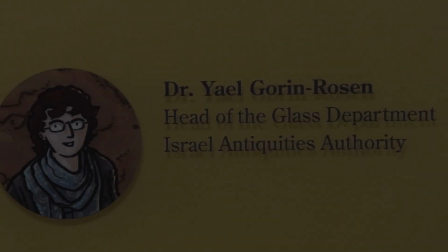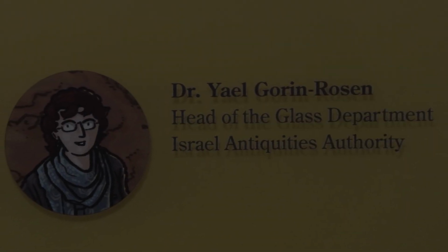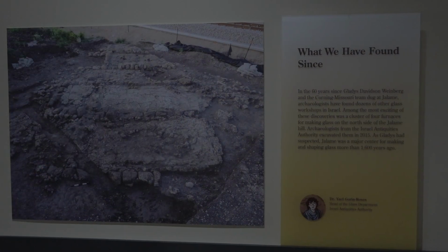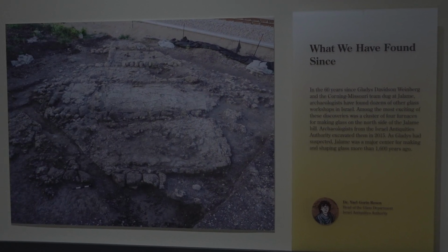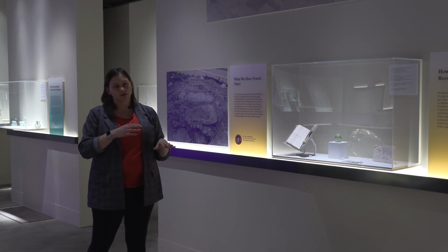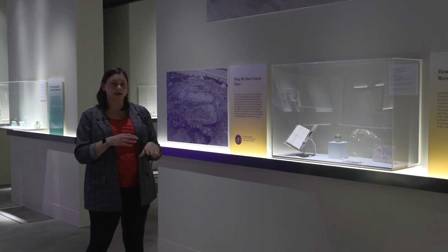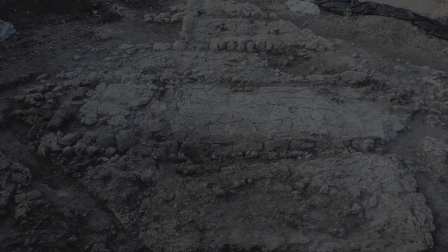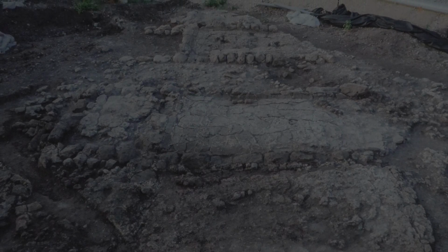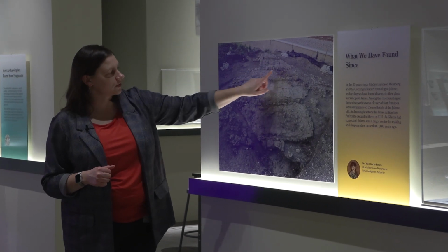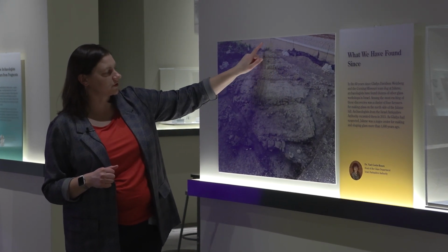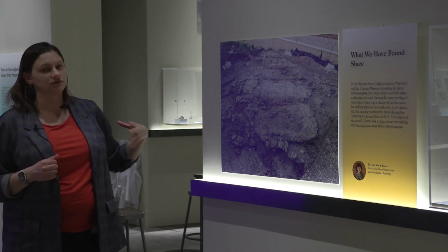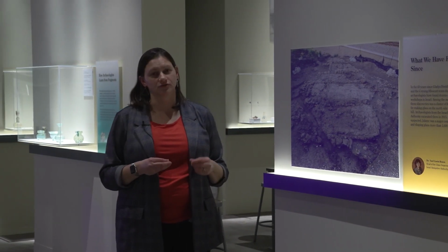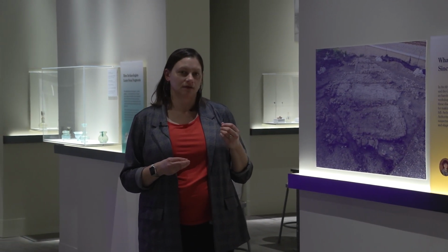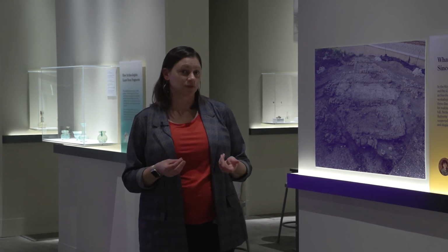In 2015, the Israel Antiquities Authority was excavating at the base of the hill. The Jalame workshop that was excavated in the 60s is at the top of the hill. The Israel Antiquities Authority was excavating down at the bottom, and they found this series of 4 tank furnaces. These are primary glass-making furnaces, and you can see there's 1, 2, a corridor here, and then 3 in just the corner of the 4th one. And this really verified that this area was really important for making glass in antiquity at this point in time. And that's what we're going to go talk about next.